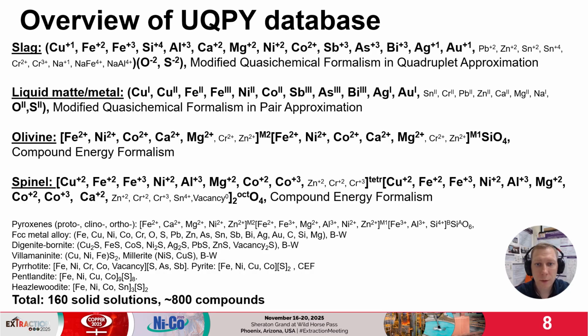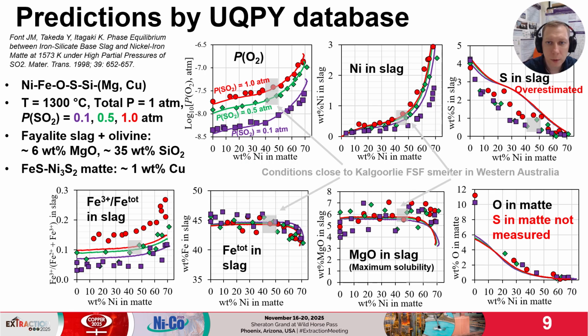But to say whether the thermodynamic database is good or not, it is not enough to see how many elements are included. The accuracy of predictions can be tested and improved by extensive literature analysis as well as targeted experimental studies. Here we demonstrate an agreement between model predictions and multi-component experiments made by Japanese researchers from Tohoku University. These are very challenging experiments to run, and predictions rely on dozens of binary and ternary systems which were modeled before. All diagrams are plotted as a function of weight percent nickel in matte.